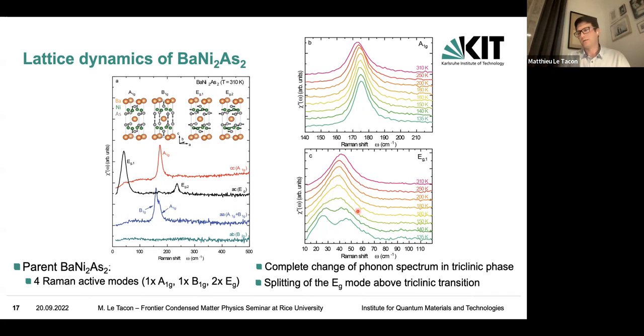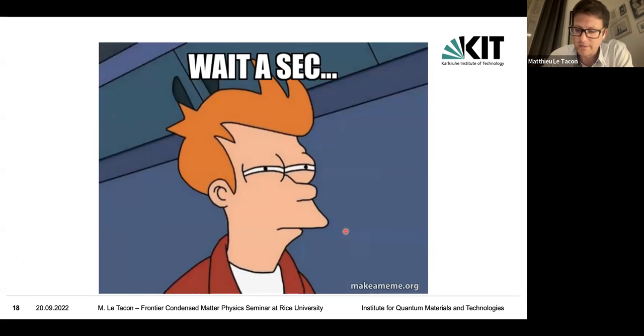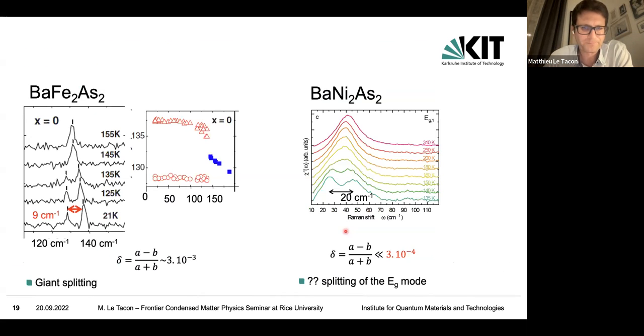Well, it splits, so that's the moment where I say, well, okay, good, the phonon splits, so that should be orthorhombic, and that's where this wait-a-second moment comes. There's something strange here: if I go back and compare to the area we wanted to, I told you this 9 wave number splitting was already very large compared to the structural distortion. And now I have a 20 wave number splitting. So a splitting which in absolute value is already twice larger, whereas a 3 times 10 to the minus 4 delta is what Christoph measures in the doped compound, where the orthorhombic distortion is significantly larger than in the parent compound.